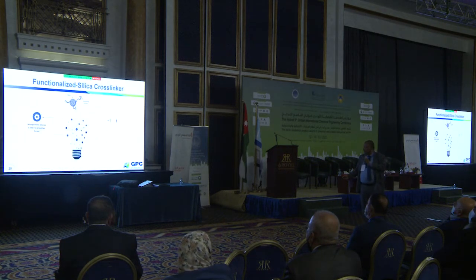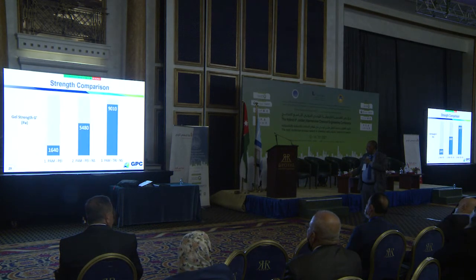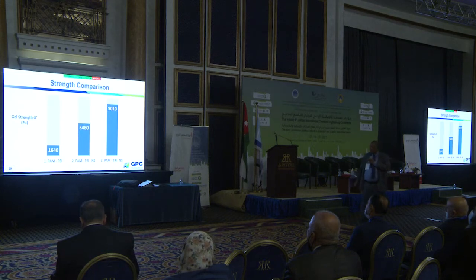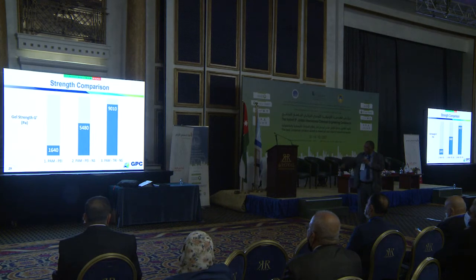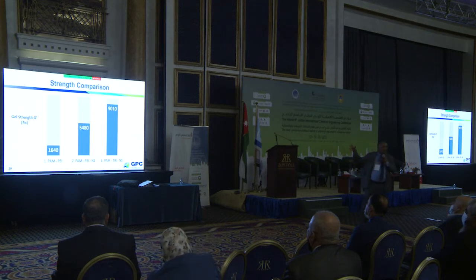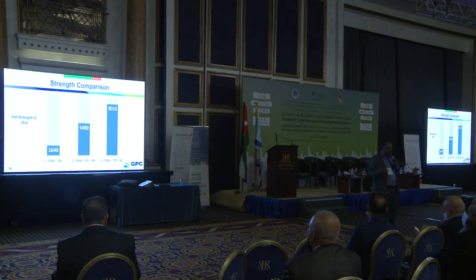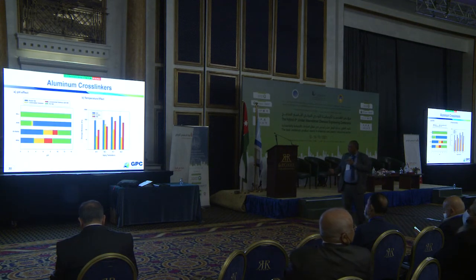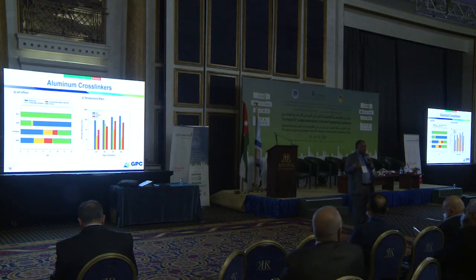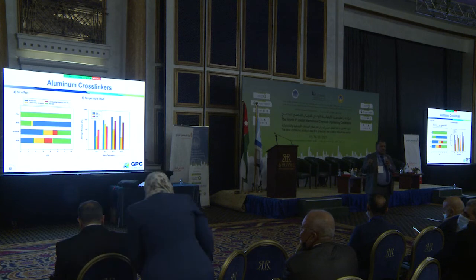And as I'll just show you in this plot, see the strength; G prime is the measure of strength. Pure PEI, the normal, versus when you add silica, non-functionalized silica plus PEI, or you add functionalized silica: major improvement. And here the improvement is mainly because we remove the mass transfer limitation. So it's basically chemical engineering issues that we're addressing in these problems, and they lead to this kind of improvement.